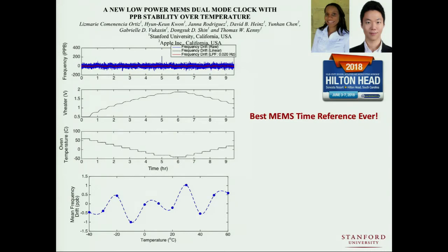We build a closed loop around the two frequencies. We apply an amount of power that keeps the Lamé mode at its turnover temperature and back out the signal. And what's happening in this experiment is the temperature of an oven that this is all sitting in is being ramped from somewhere around 60 degrees down to minus 40 and back up in steps every half hour. The frequency output of the clock is not moving around. There's no strong temperature coefficient. If we average within each segment, we're seeing that the output frequency is only changing by around 1 part per billion over this entire temperature range. We can sweep back and forth.